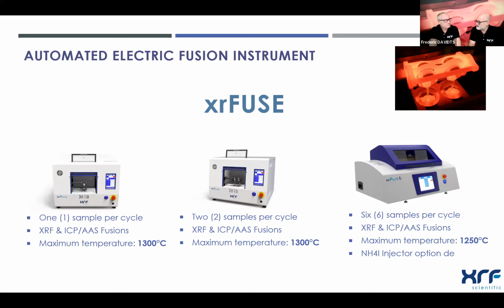For example, the maximum heating temperature can now be set at 1,300 degrees, but we also have new features to increase the cooling process, not only of the molds but also the crucibles, all made to allow the operator to be in a safe environment and condition, and of course increase the throughput. And of course we have a 6-position machine, so if you do, I would say, 100 samples per day, that's what you need, and more, of course.